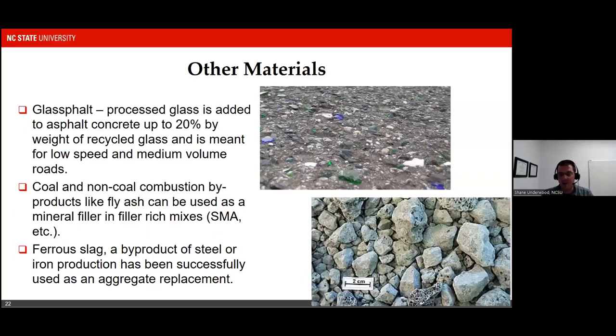One of the obvious problems with using ferrous slag is the porosity of the aggregates, and you can see that in this picture here, where these obviously look very, very porous. And so generally speaking, they're used at a fairly low dosage rate so as not to increase significantly the cost of the material due to binder absorption.